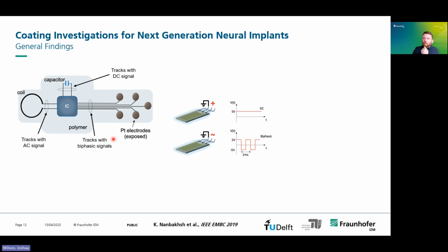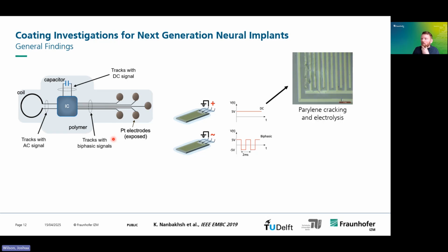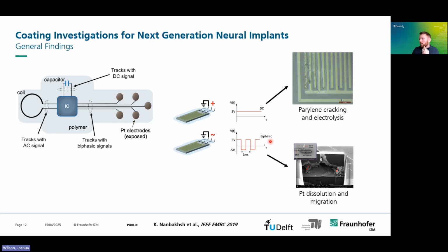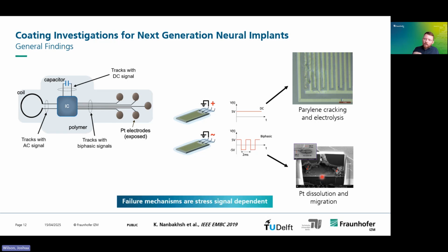So what we investigated was what happens if we use different signals on our test structures. Will the results be the same? And in fact, the answer is no. In one case where we applied DC, we saw cracking of the coating. And in another case where we applied biphasic signal, we saw the metal dissolving, corroding, migrating. So what this tells us is the failure mechanism of the device is also dependent on the stress signal. So whichever signals you have in your device, these are going to affect the failure.